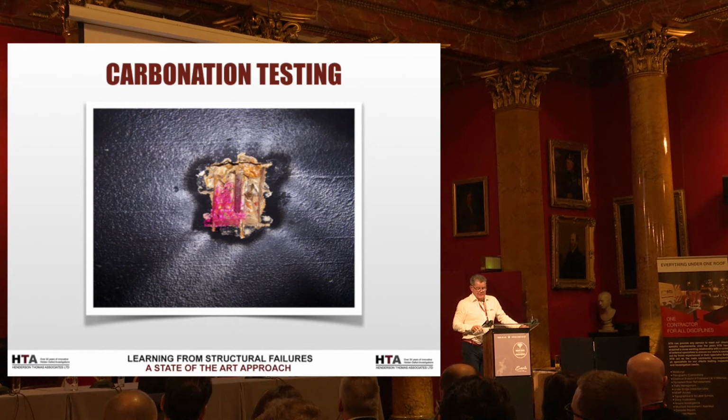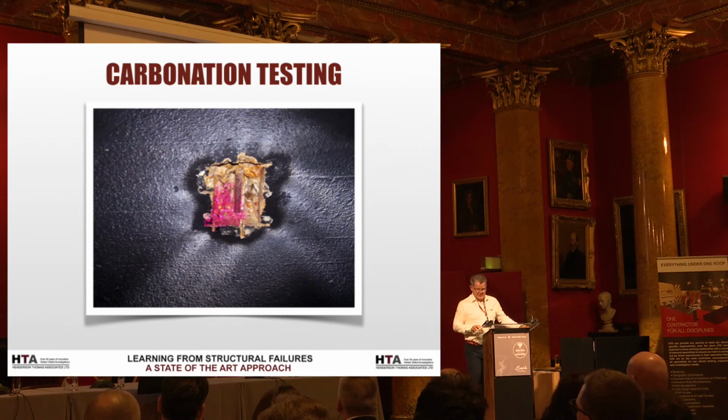However, carbon dioxide in the atmosphere can produce a weak acid as it dissolves into concrete, which causes carbonation. The carbonation reduces the alkalinity of the concrete to a point that we can pick it up with an indicator solution. It doesn't make the concrete acidic or even neutral. It just reduces the alkalinity of it, which reduces that protective alkalinity and will allow the reinforcing bar to corrode.